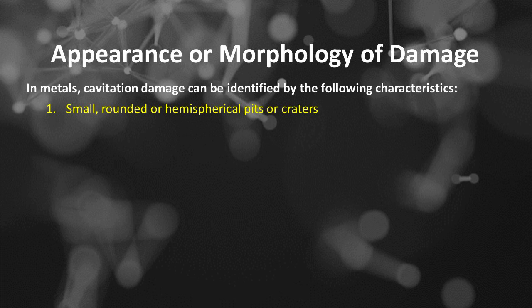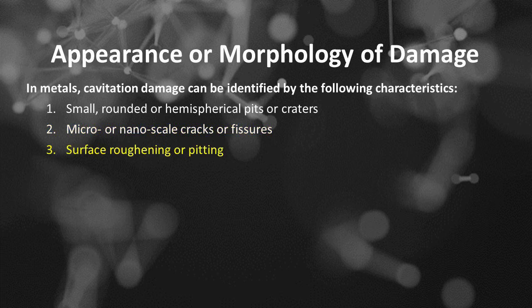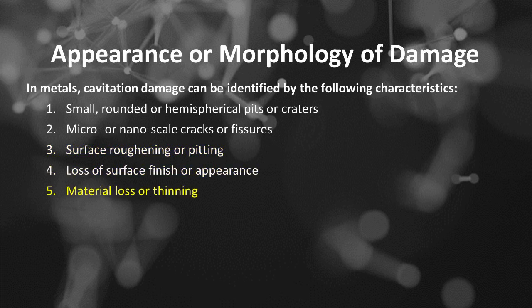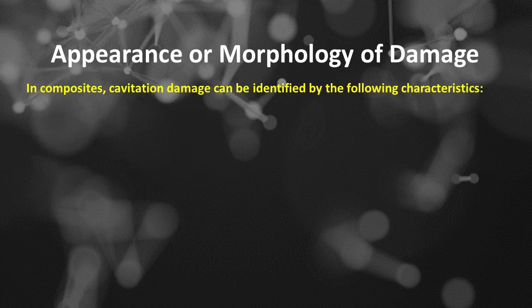Number 1 is small, rounded or hemispherical pits or craters. Number 2 is micro or nanoscale cracks or fissures. Number 3 is surface roughening or pitting. Number 4 is loss of surface finish or appearance. Number 5 is material loss or thinning. In composites, cavitation damage can be identified by the following characteristics. Number 1 is blisters or bubbles on the surface.